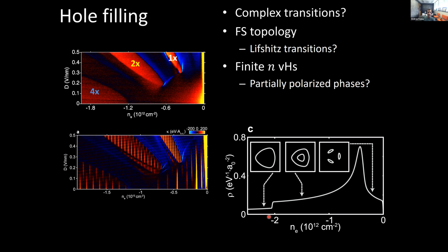And so you can try to work out everything that's going on here using finite magnetic field capacitance measurements and zero magnetic field capacitance measurements, resistivity measurements, and so on. And basically, what you find is that there's a very complicated in and out between states that have Lifshitz transitions where you nucleate new Fermi surfaces, and also phases that are not completely spin and valley polarized, but rather are partially polarized within this set of flavors in the same way that most ferromagnets are simply partially polarized. They're not fully a half metal. If you take a piece of iron, there's some small spin imbalance, but they're just kind of partially polarized.